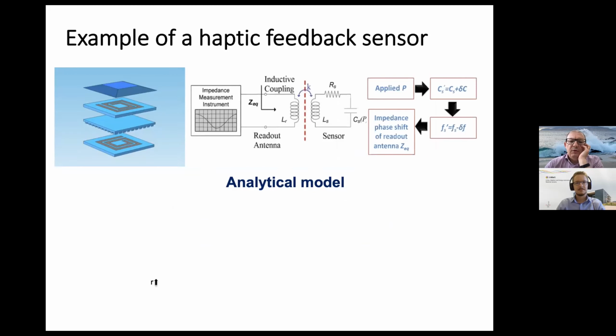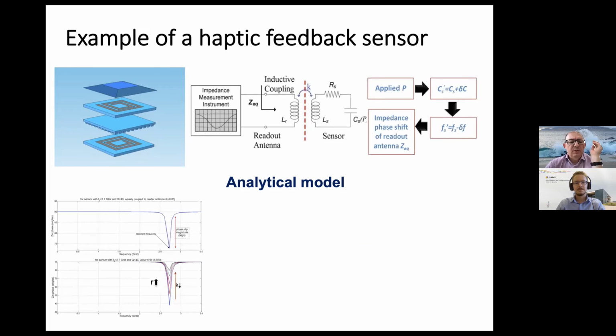And what you can do is have the powering system embedded, for example, inside the finger, and the actual reader antenna might be the object you want to detect. So you rely on a change of pressure, which will give you a change of capacitance, and therefore a change of frequency because you have a resonance structure. And by looking at this change of frequency, you can deduce the applied pressure. So this is an example where you see that shift of frequency depending on the coupling coefficient, which is a function of the distance between your sensor and your readout, as well as a function of the pressure.